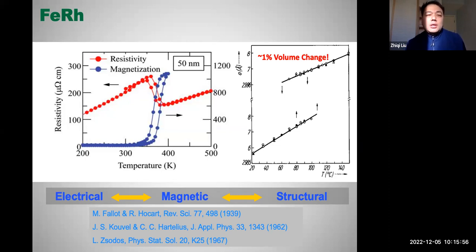This material is so-called iron rhodium. It's a metastable, it's a metamagnetic material. At low temperatures, it's antiferromagnetic. You can see from the left figure, the magnetization is negligible. This blue curve. But above 360 K, it goes into a metamagnetic transition, and finally it becomes a ferromagnetic metal.